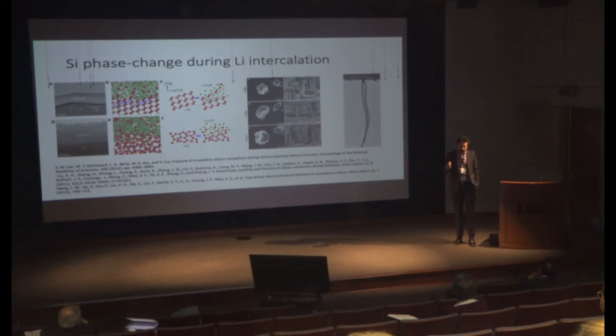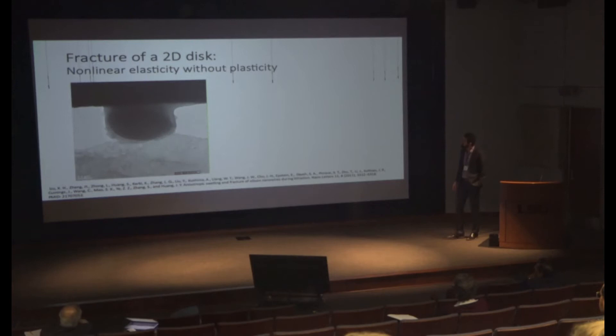How do these things fracture? This is a silicon sphere—they lithiate from the top, and as you can see the thing swells and then cracks on the outside. But on a fundamental level, if there is no inelasticity and you put in something that makes you expand, you're making compressive stresses on your surface, which is not going to make you crack.